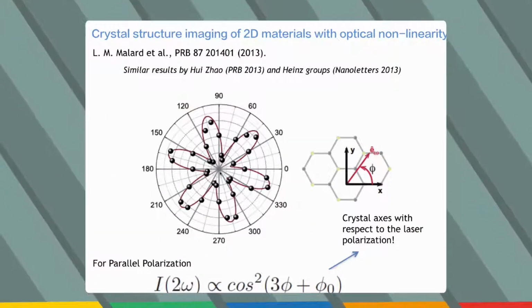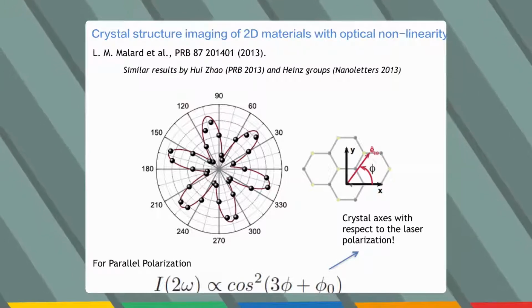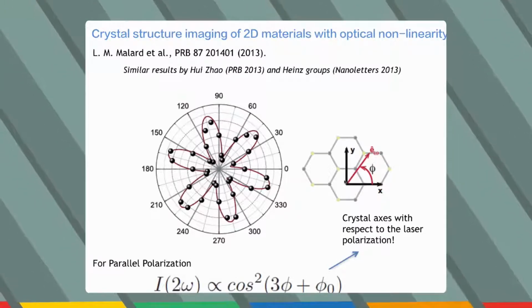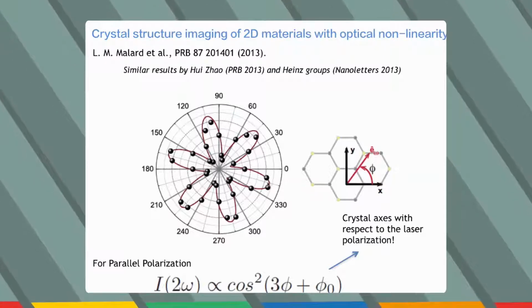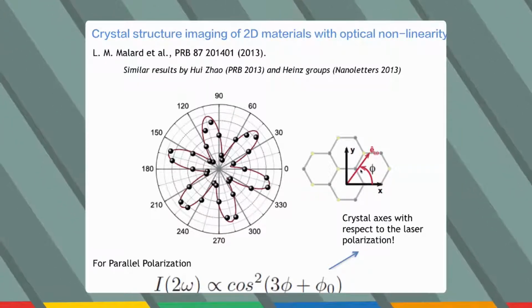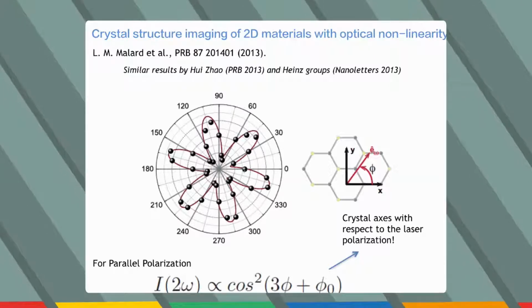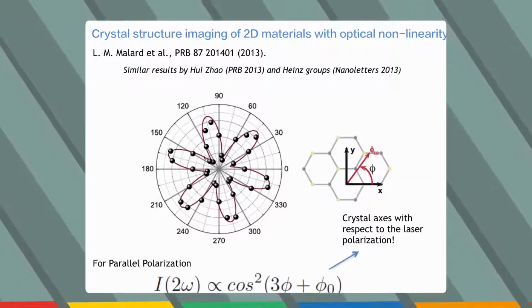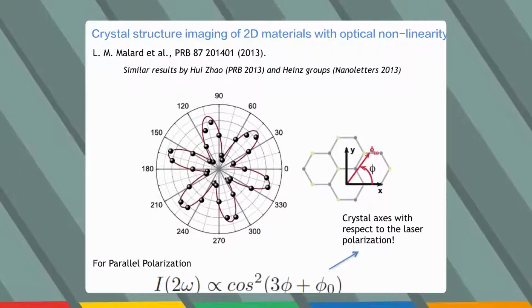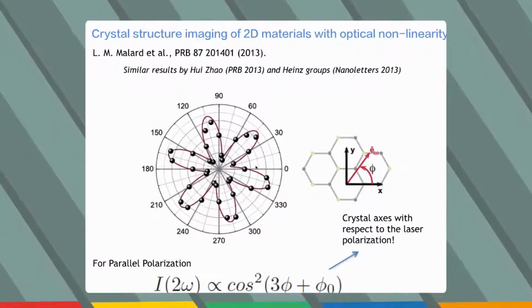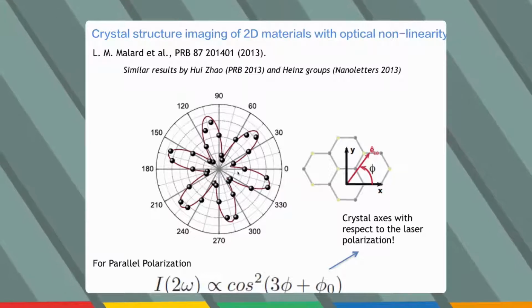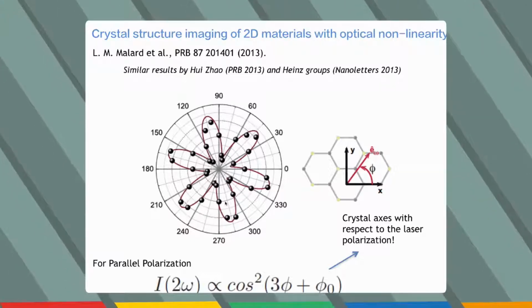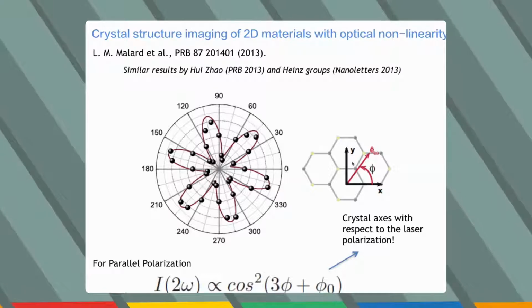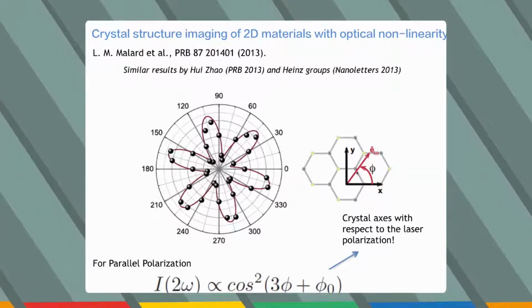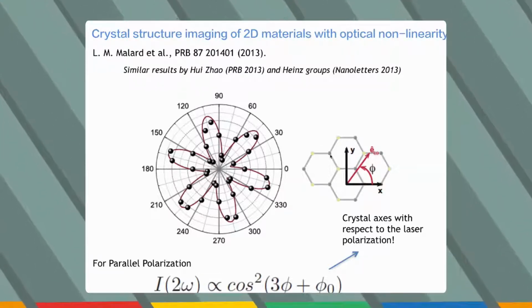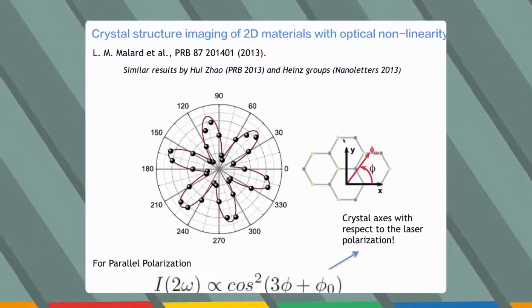What else can we do? We can fix a polarizer in front of the detector, and then we rotate the sample. And what we see is that the intensity of the second harmonic changes like this. So we get this 6-fold pattern. We can calculate why this happens, and this basically tells us that the symmetry of the crystal is this hexagonal pattern. You have molybdenum here and so forth.